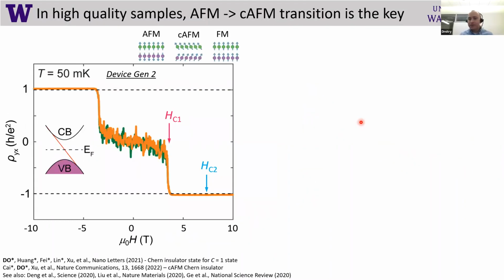But that's not essentially the full story. So now we discovered if we build the high quality samples, for that we first of all needed crystals with less defects, and also we needed higher quality fabrications. So I call it device generation 2 here. What we found in device generation 2, as soon as we get transition from antiferromagnetic to canted antiferromagnetic state, we get immediately a very sharp transition to Chern number 1.